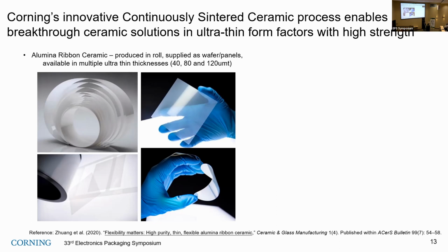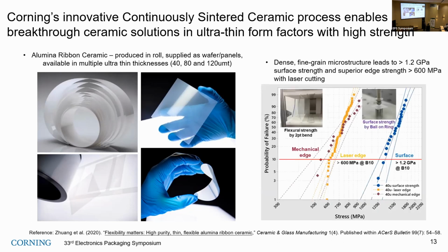Our current capability is a 4-inch width, and lengthwise it can be roll-to-roll. We can make 3 different thicknesses now: 40 micron, 80 micron, and 120 micron, which is our maximum thickness for this roll-to-roll continuous sintered alumina. It is also very pure alumina, 99%. So it has a very fine grain structure that gives us very good surface strength of greater than 1.2 gigapascal. We tested with the ball and ring test that I showed in the microLED glass testing, and it also has a very good mechanical edge after laser cutting of these ceramics.